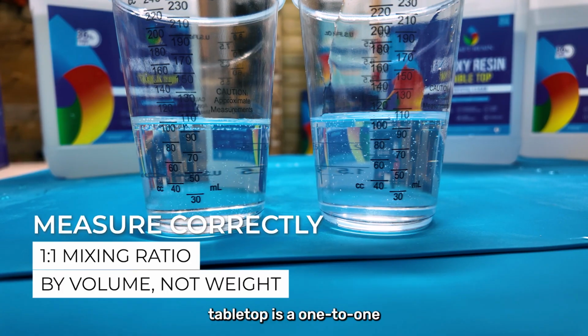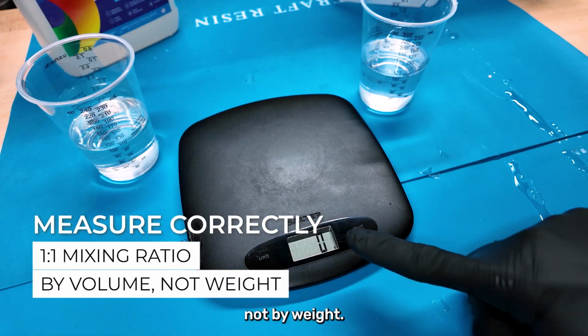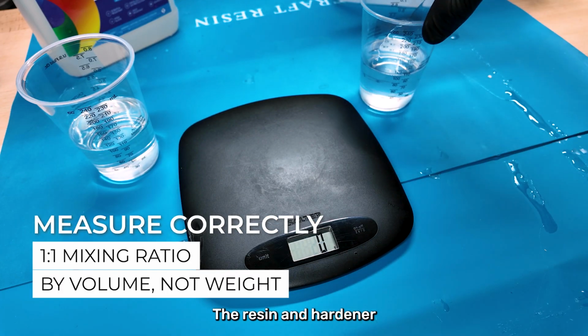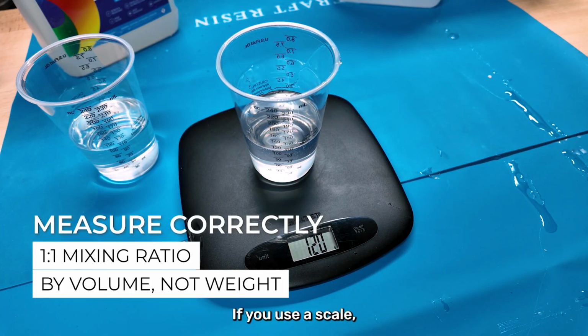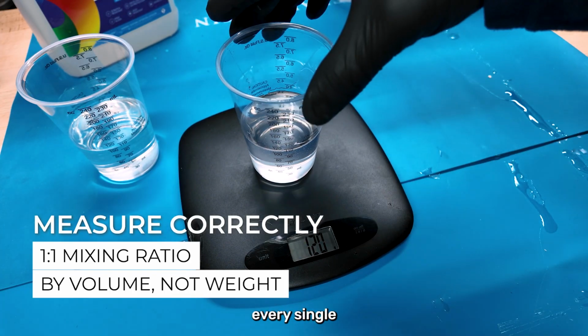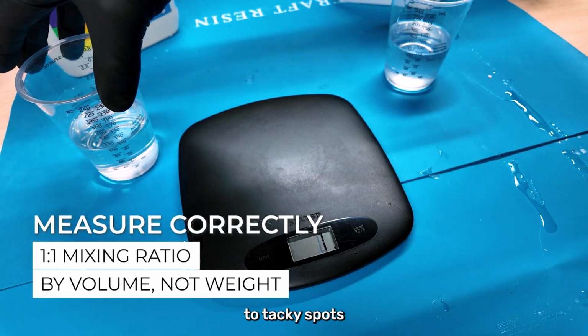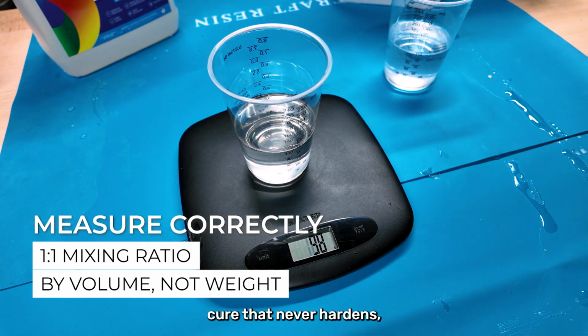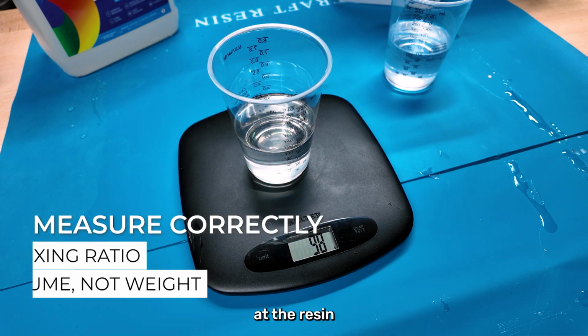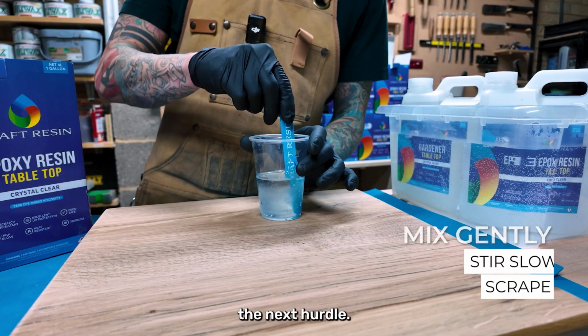Craft Resin Tabletop is a 1-to-1 formula by volume, not by weight. The resin and hardener have different weights. If you use a scale, your ratio will be wrong every single time. This leads to tacky spots or a soft, rubbery cure that never hardens, and then you're mad at the resin for no reason. Mixing is the next hurdle.